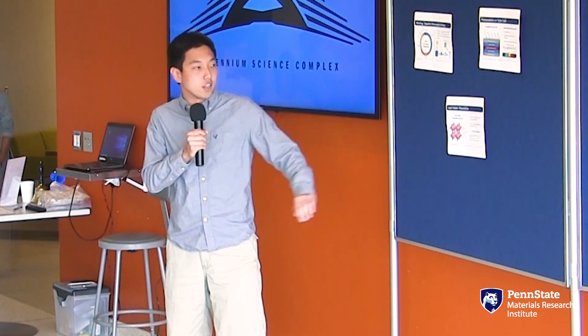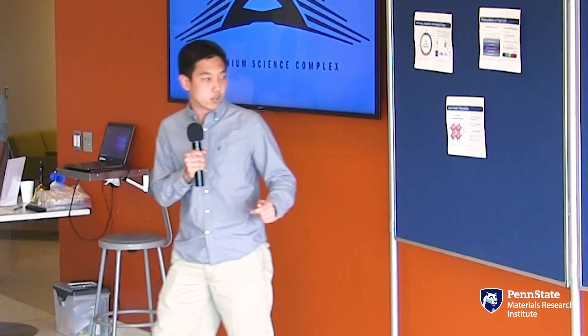This really limits the feasibility of lead halide perovskites in terms of direct synthesis. My research is focused on taking known lead halide perovskite templates and using cation exchange to selectively target this blue sphere, leaving everything else in place and substituting something smaller or larger, thereby generalizing a synthetic method to expand the range of known halide perovskites.